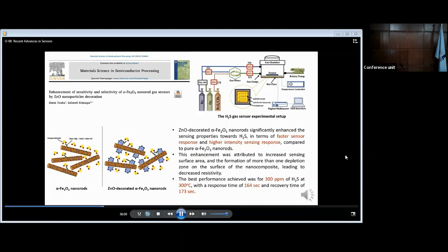Let us start with this first example. This paper is titled Enhancement of the Sensitivity and Selectivity of Alpha Ferric Oxide Nanorod Gas Sensors by Zinc Oxide Nanoparticles Decoration. Here, alpha ferric oxide nanorods were decorated using zinc oxide nanoparticles, which significantly enhanced the sensing properties towards hydrogen sulfide in terms of faster sensor response and higher intensity sensing response compared to pure alpha ferric oxide nanorods.